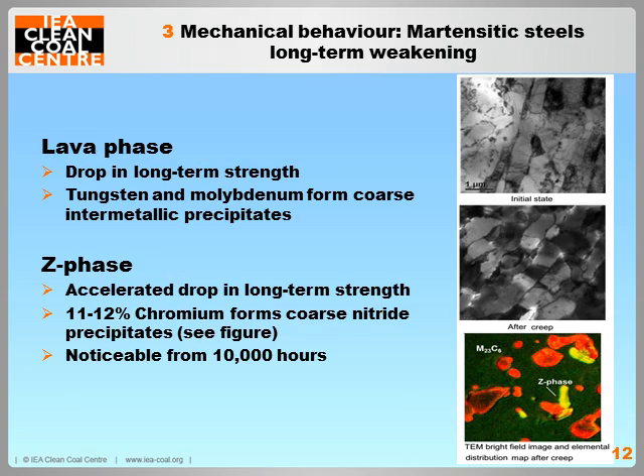Higher chromium martensitic steels with 11 to 12% chromium have an accelerated drop in long-term creep resistance, which is more than what can be explained by Laves phase alone. The increased chromium levels cause precipitation of coarse nitrides known as Z phase. So the combination of Laves phase and Z phase means that higher chromium martensitic steels are weaker than lower chromium martensitic steels.